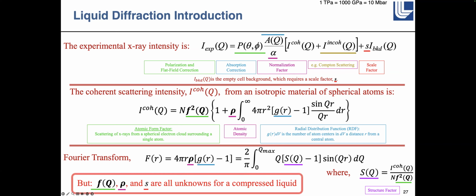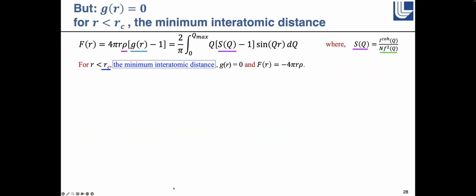The problem is that the form factor, the density, and the scale factor of the background are all unknowns in a diamond cell or in a dynamic compression experiment, because in a diamond cell, your background is going to change because your gasket changes shape. In a dynamic experiment, the ablation plasma is going to be different in different densities on each shot. The density is obviously changing. That's not known a priori. And the form factor, even the shape of the atoms is going to change with compression. And so all three of these change. And so many people that do liquid diffraction say, well, it's impossible to do at high pressure. But when I was at the CEA, we came up with a way to do it.